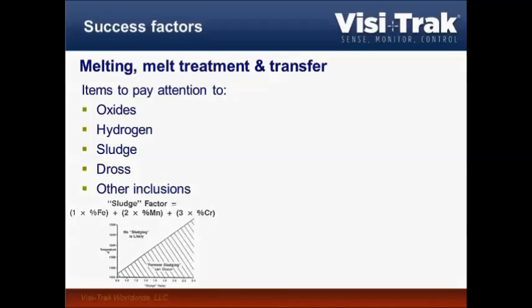Sludge is a big problem, and most of you are probably familiar with the sludge factor. It's 1 times iron plus 2 times the manganese plus 3 times chromium. I mention that here because when we talk about high integrity die castings, we lower the iron content. As we've seen before, typical die casting alloys 1.3% iron. So you can already see that gets you pretty high on that curve here in terms of sludge factor, plus 2 times the manganese. And for high integrity die castings, we actually replace iron with manganese. So manganese is twice as harmful for our sludge factor as iron is, and therefore we have to really watch out with our chemistry so we don't create a big sludge problem.